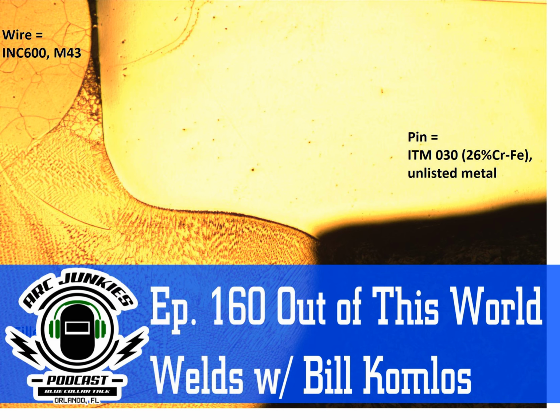So I'm just thinking to myself, my gosh almighty, I've gone back to one of the most basic, unsophisticated weld base metals, and just the grunt code, right? I mean, it's all going to be stuck in concrete anyway. You don't even get to look at your welds to figure out how good a welder you are. It just gets dumped into the mud and it's done. And I'm going, but here I am using D1.4 in order to justify a good weld, but because the code doesn't describe this particular joint configuration, I have to pull it and then write a little masterpiece on why this is a valid axial test to test the shear strength of these wires as they go into tension. Because this is a shear.